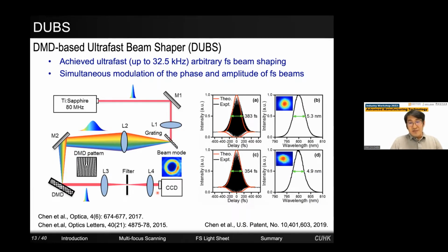Some people may wonder how come this was not done in the past. The reason is that for the longest time, the DMD was considered not compatible with the femtosecond laser because the pixels on the DMD are too small, which causes dispersion. And we address the issue with this dispersion compensation design as shown in the US patent here. As a result, when we measure the pulse width after the DMD, it shows a very narrow pulse width and the diffraction effect has been entirely removed.